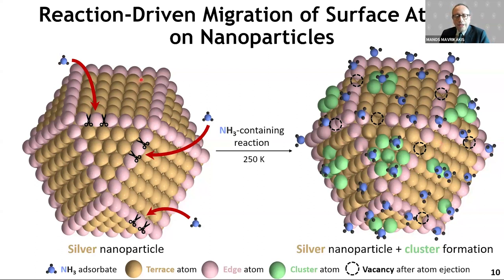So what's the difference here? You have the pre-existing terraces, facets that give you the original vision for the active sites in the nanoparticle. But in addition, you have these structures, the green colored structures, that is a heptamer, a tetramer, another tetramer, a trimer, etc., a dimer. And the question is, which one of these sites now, the old-fashioned sites here, of the extended surfaces, step edges, are dominant, or these new features that are developing under reactive environment, breaking the metal-metal bonds, could be dominating reactivity? So that's what we are interested in. So this is the picture I would like for you guys to keep in mind at the end of this lecture, if everything else goes away.